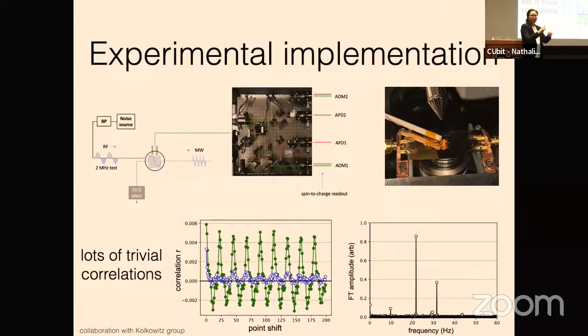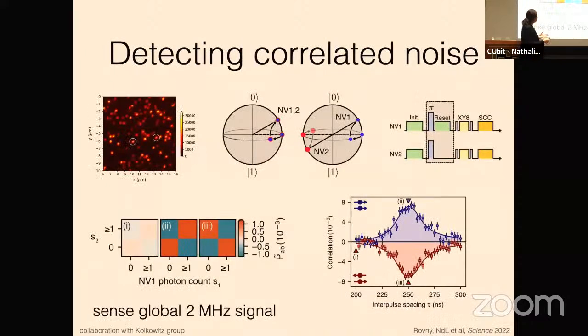But then because you save all of this data, you can just sort of point shift your data, right? And then see if there are correlations that show up anywhere else. And we saw this clear sort of periodic behavior. And actually, we somehow found this out from June's lab that your table can be floating, but then not really floating, and you have a little touch on one of the legs. Don't remember who told us that fact. But we then went hunting for that, and were able to beat down all of these spurious correlations. So it's much harder to build a 2NV experiment than a single NV experiment, but after a lot of pain, it is possible. So here is now an example of detecting correlated noise with 2NV centers.